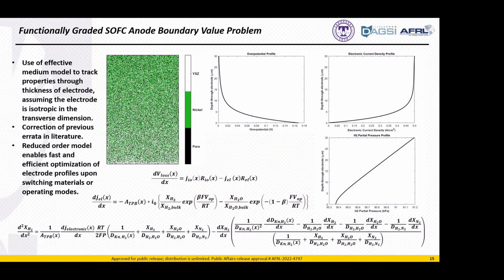And the subsequent research has shown that electron transfer is incredibly fast at these temperatures. It's probably the diffusive transport in the cathode materials which is governing the rates, or the dissociation reaction at some temperatures, which are governing the kinetic rates. And they all have these Arrhenius type of behavior. So the Butler-Volmer-like equations fit very well, but some people in the solid oxide field get very offended when we keep using the word Butler-Volmer, because they believe that that term should only be used for electron transfer. So I've used in the past Butler-Volmer-like, or carries the form of a Butler-Volmer equation, but it is not. We're not assuming that the electron transfer reaction is the rate limiting step at the triple phase interface. Yeah.